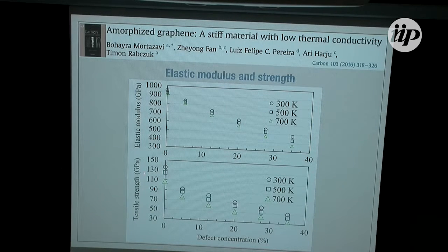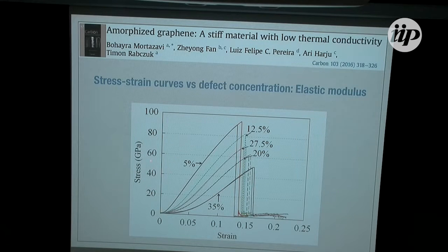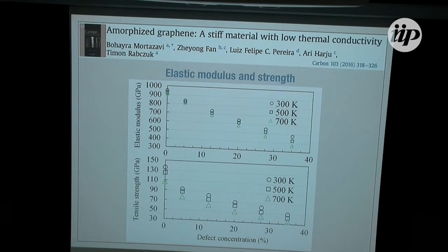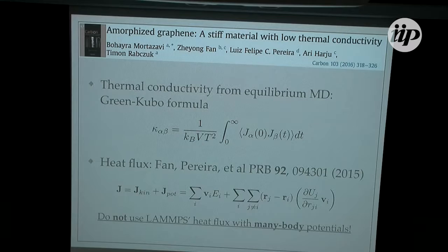So this is the elastic modulus and the tensile strength, the stress at which it breaks. They both decrease as we increase the defect concentration. This is the tensile strength, the stress at which it breaks, and so it decreases with the defect concentration. But regardless, this material at 300K still has an elastic modulus of 500 gigapascal. This is 50% of graphene's elastic modulus, so it's very high.